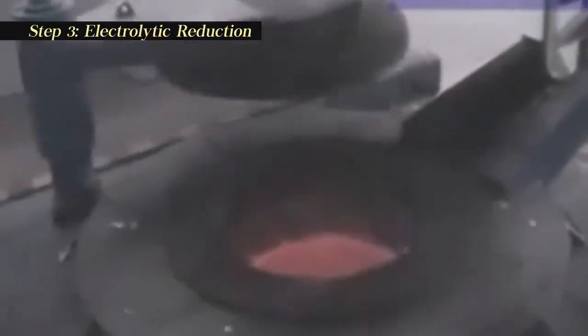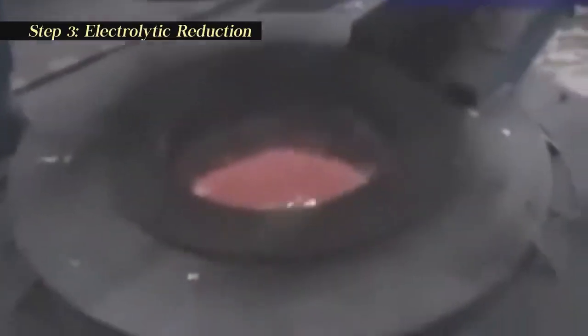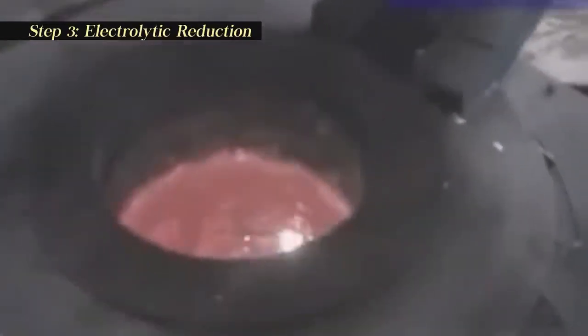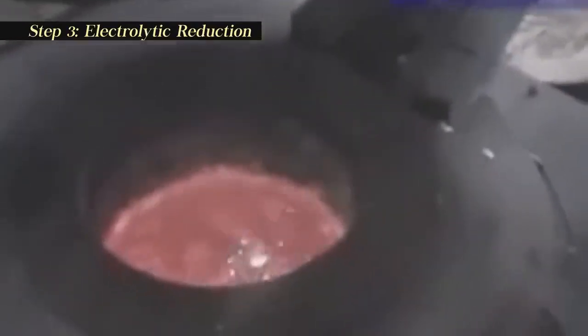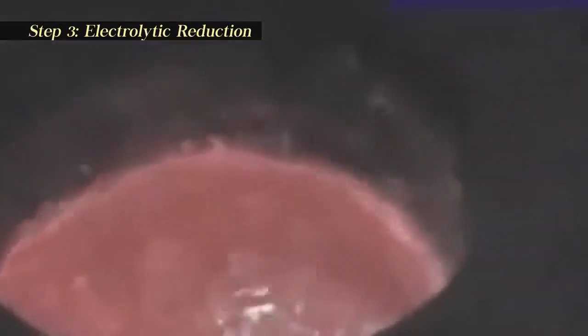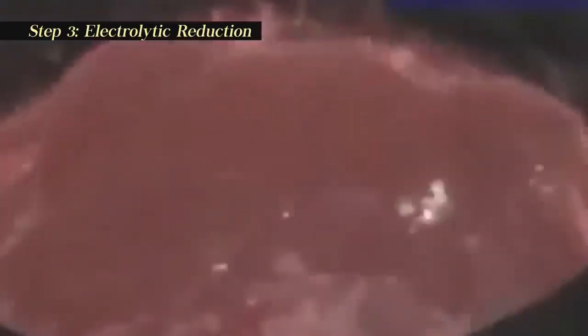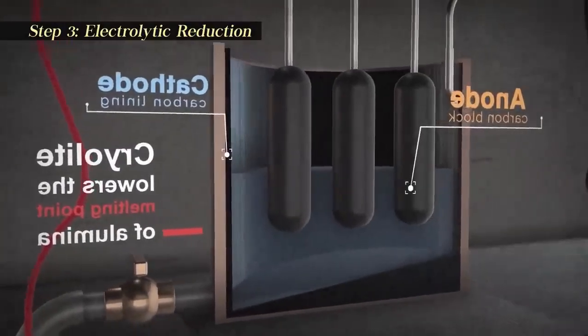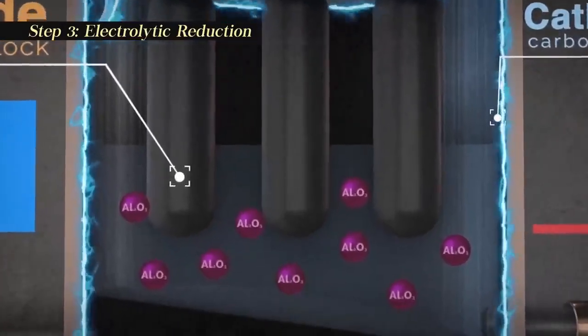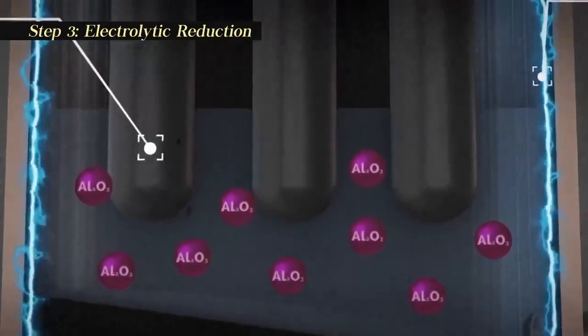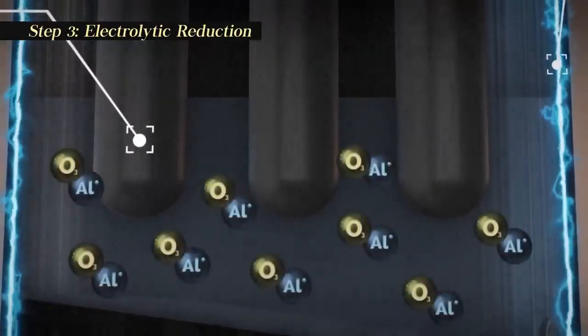per year. Within the reduction pot, alumina crystals are dissolved into molten cryolite at a temperature of 1760 to 1780 degrees Fahrenheit, 960 to 970 degrees Celsius, to form an electrolyte solution that will conduct electricity from the carbon rods to the carbon-lined bed of the pot. Next, an electric current is run through the cryolite, causing a crust to form over the top of the alumina melt. When additional alumina is periodically stirred into the mixture, this crust is broken and stirred in as well.